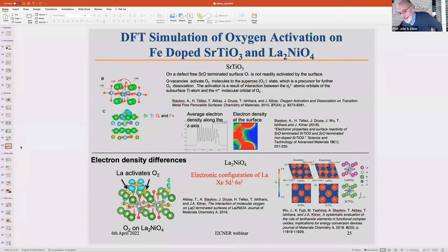Okay. Right. Okay, Quanti, I'll try and get an answer to this. I mean, there's quite a bit of evidence. If you look back, let's just think about the carbon dioxide molecule itself. We've done a little bit of work which has not been published, but Eric Wachsmann did some work some time ago where he was looking with gas phase mass spectrometry, and he saw the same sort of things that Stephen was talking about: the oxygen exchange or the tracer exchange is accelerated in the presence of CO2. So again, the CO2 molecule will exchange oxygen faster than the O2 molecule.